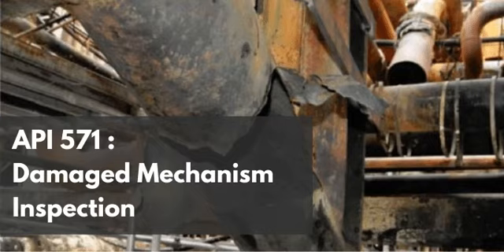Yes, it is. And this is a point that completely contradicts the instincts of many mechanical engineers. With many damage mechanisms like severe fatigue cracking or certain forms of brittle fracture, taking a grinder to an active crack is incredibly dangerous. Oh, absolutely. The localized heat input and the mechanical stress of the grinding wheel can act as a wedge, causing the crack to suddenly run or propagate deeper into the material.